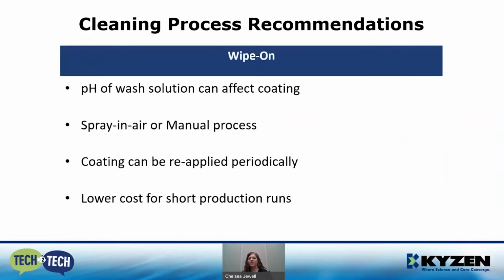So, cleaning process recommendations. With a wipe-on coating, we have observed that the pH of the wash solution, even down to the rinse sometimes, can affect this coating. Typically, we recommend spray and air or manual processes for our wipe-on coating. The nice thing about it is that you can apply it on-site. So if you notice that the coating is starting to wear or it's been removed, you can have an operator reapply that coating.